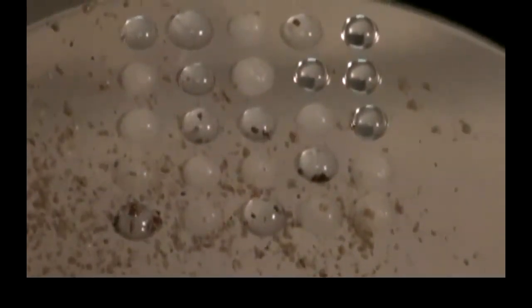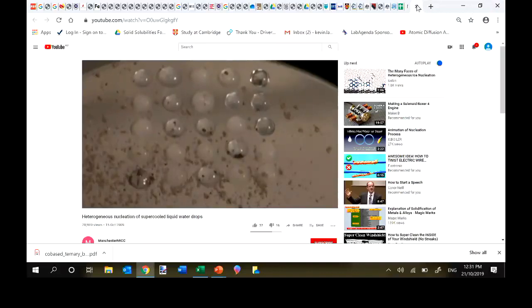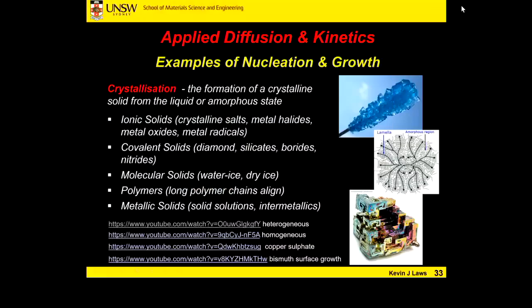Okay, so essentially, I'll just turn that off. With this experiment, we've got our water droplets on a cooled stage. The stage is continuously cooled, right, to lower temperatures below the freezing point of water or whatever the liquid was. And we saw there a couple of those droplets solidify, crystallize very quickly. And that could have been because those droplets had an impurity, or the surface below them had a scratch or something in it that acted as an inoculation point, or that could have been true homogeneous nucleation.